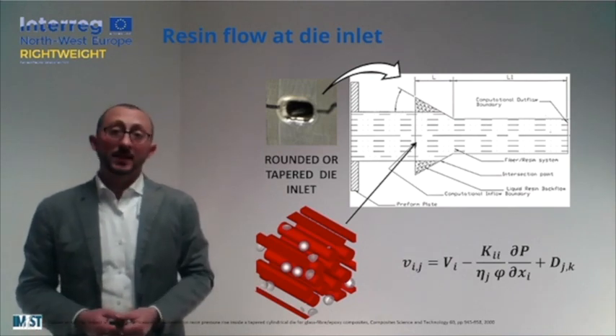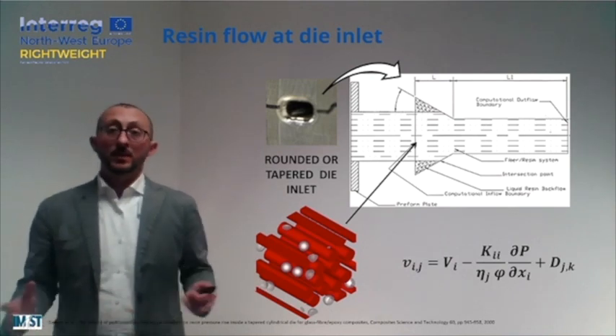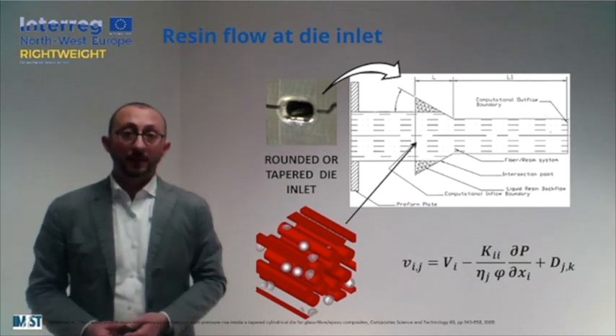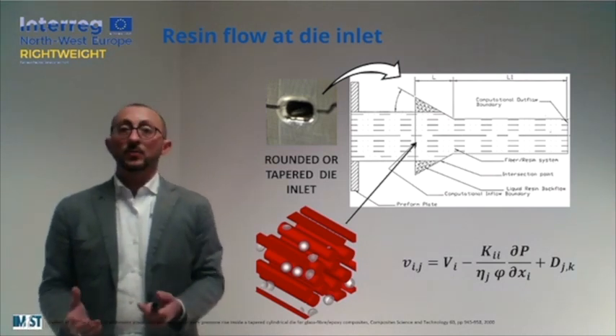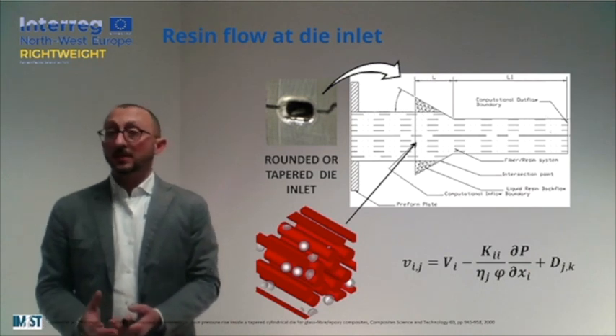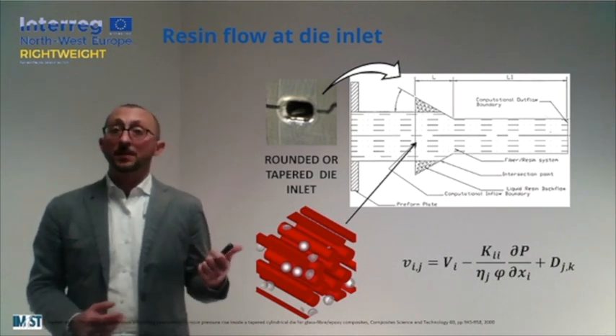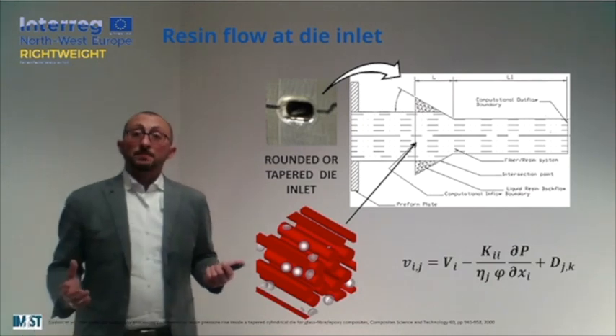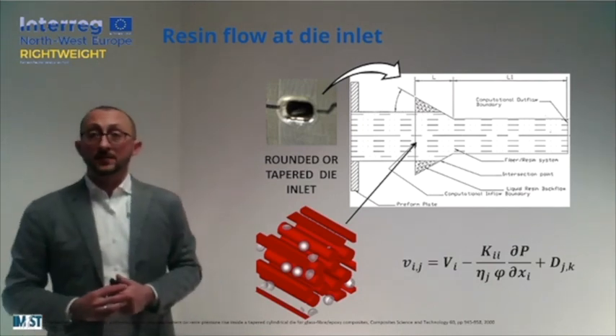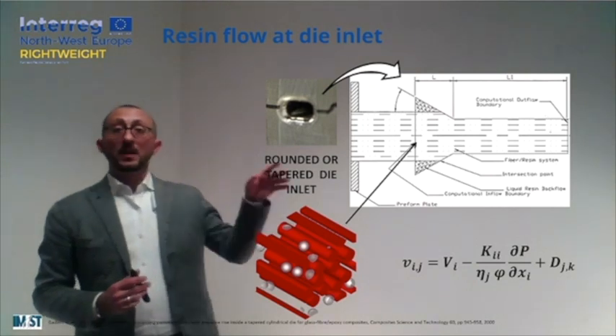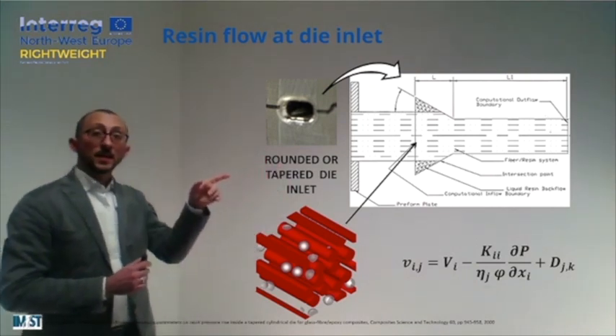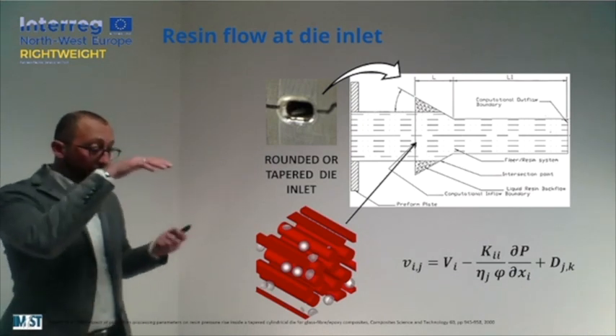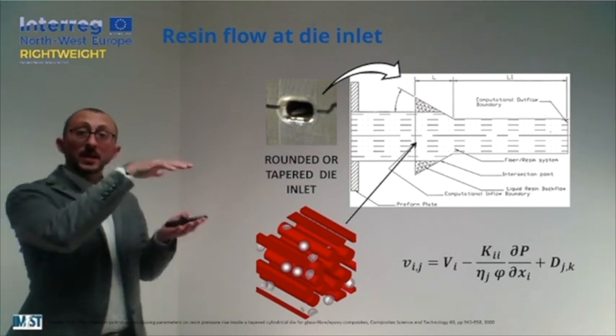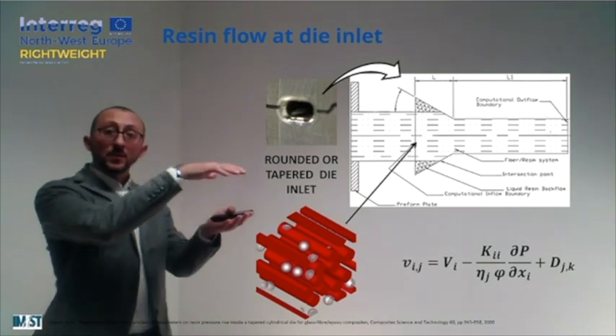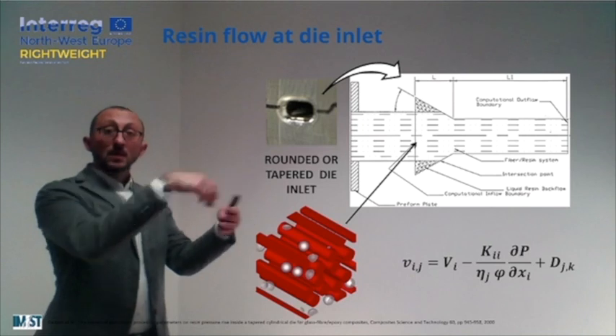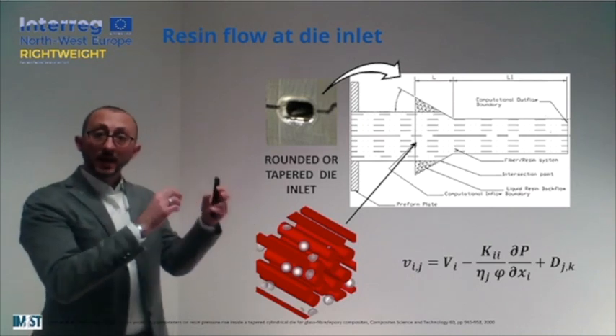And since voids are the worst enemies of each composite material, if we want to achieve a good, strong product, we should remove these bubbles here. And here the effect of the inlet is very important, because if we have a look at the schematic that is there, we can imagine that the fibers behave like a porous traveling material. So they are moving inside the cavity, impregnated with resin, with some air.